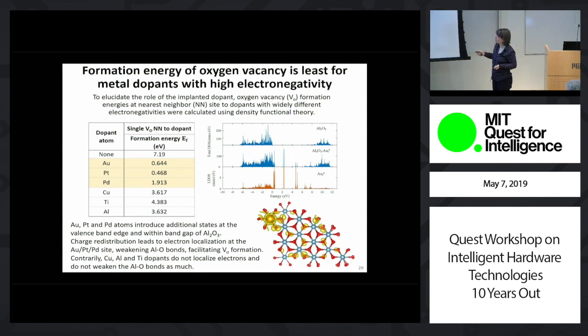And if you look at the formation energy of oxygen vacancies in the vicinity of these implanted atoms in alumina, you see substantial decrease of that energy cost compared to the undoped alumina. So it's really pretty much impossible to reduce alumina if you don't dope it. And gold, platinum, palladium reduce that formation energy substantially. Copper, titanium, aluminum also do that, but not significantly enough.